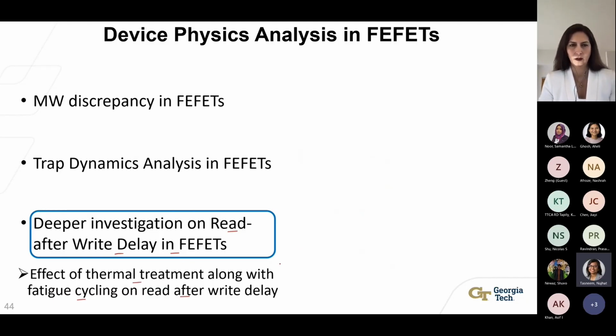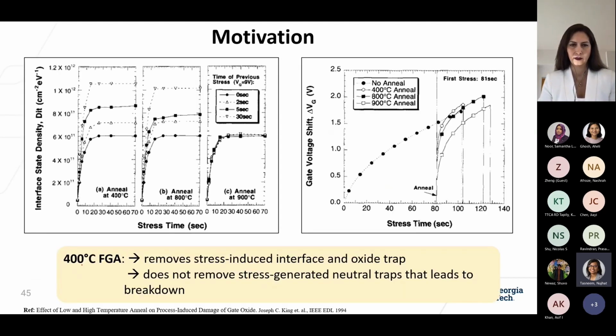So the motivation for this work came from an older article, which showed that 400 degrees Celsius forming gas anneal can passivate the interface traps that are created in the initial stress, which is shown by this figure over here. And the second figure shows that the stress also creates additional bulk neutral traps, which actually leads to the oxide breakdown. And these traps cannot be passivated by 400 degrees Celsius anneal. So the bottom line here is that 400 degrees Celsius forming gas anneal can remove stress-induced interface and oxide traps, but it does not passivate stress-generated neutral traps that lead to breakdown.